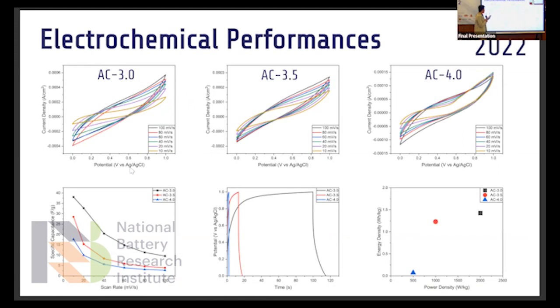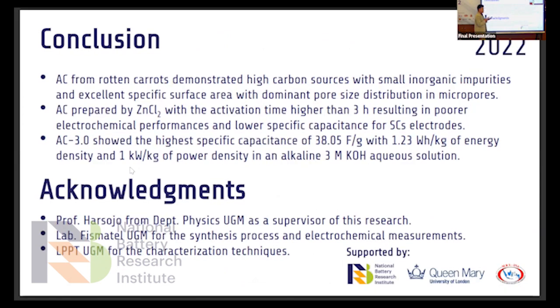Next. The last one is the result from CV and GCD. The electrochemical performance is measured by a standard 3-electrode system in aqueous electrolyte. As seen in the CV curves, the highest peak occurs at AC3, confirming that an activation time higher than 3 hours affects the electrode stability and decreases the capacitance. Regardless, all samples exhibit a power density higher than 500 watts per kilogram, with the highest energy density of 1.23 watt hours per kilogram for AC3.